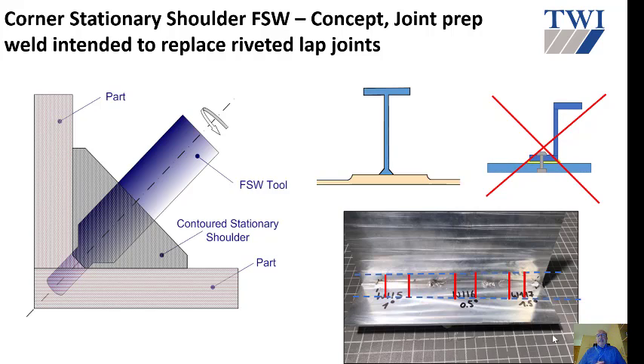So when we joined, we learned that the process, shown on the left here, means that the shoulder is stationary, so it doesn't move, only the pin moves. Well, actually it's called a probe because it's rather large, sometimes 5 millimeter in diameter at the tip, and it's rotating in this case counterclockwise, bringing the advancing side from, in this case, part 1, which is 7050, toward the 2024 side, which is the skin. The geometry tries to replace rivets. By the way, the project was looking at Airbus 320 aircraft cargo doors. You will see that actually the demonstrators were welded using this process.